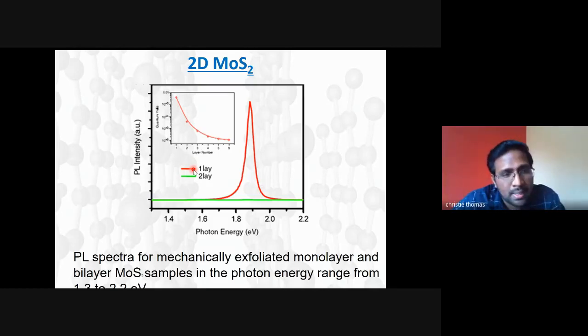Okay, but an appreciable photoluminescence was observed in a few layer MoS2 samples, and most surprisingly, very bright photoluminescence was detected in monolayer MoS2. Okay, that's what you see here. The red curve is one layer MoS2, and the green curve is two layer MoS2. Okay, you can see a strong PL peak for one layer MoS2, and for two layer it's comparatively very weak.